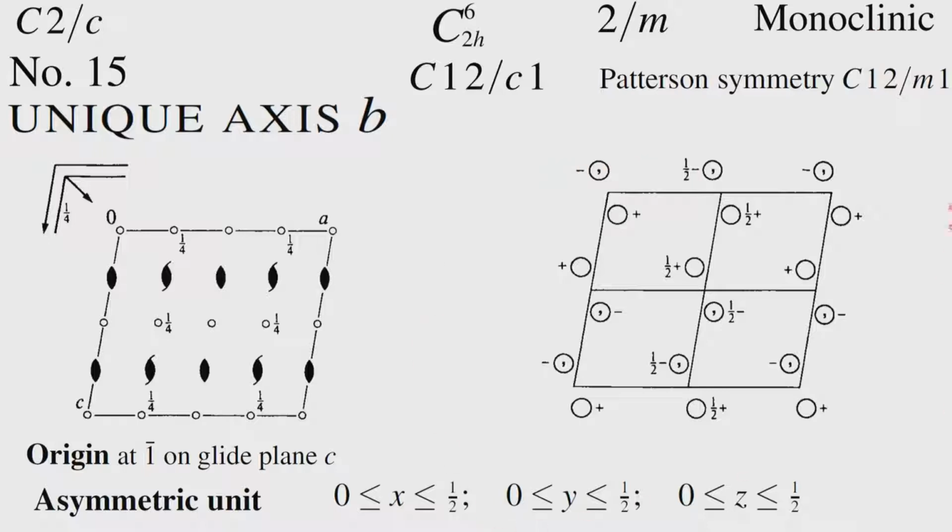So, the equivalent point diagram is shown here, and you see now the asymmetric unit is halved in all three directions. So, it is half here, half there and half there. So, the moment that it is half, this fellow will not come up, and therefore, there are two of them present, one here and one there, or for that matter we are taking half the unit. So, this is half the unit and that is half the unit. So, there are two additional points due to the presence of the C centered lattice. So, since it is C centered lattice, the asymmetric unit will consist of two independent molecules. They are not dependent on each other anymore, and therefore, there will be two of those.